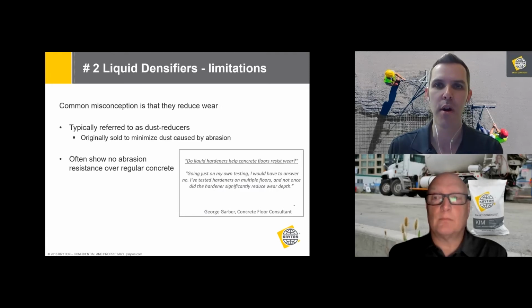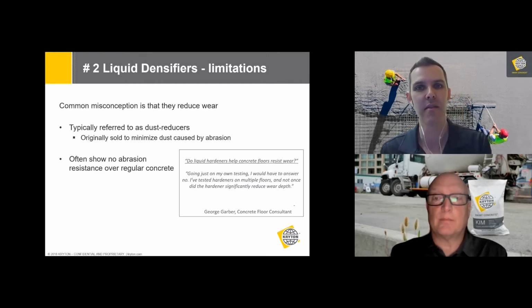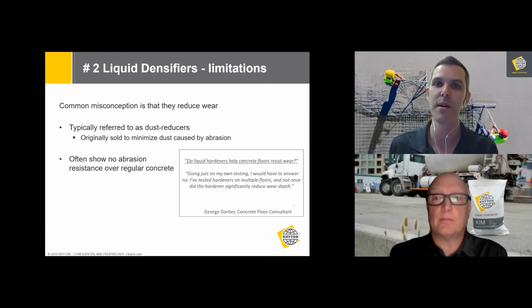Now, this basic reaction product of reacting with calcium hydroxide to strengthen the paste is quite similar to how SCMs work, such as fly ash, slag, or silica fume. So one of the consequences of using a liquid hardener is they may then start competing with your fly ash or slag for this calcium hydroxide. In fact, so much so that many suppliers of these products recommend limiting the amount of fly ash or slag you use in your concrete, or they may recommend delaying the application for up to 28 days because they want to allow the concrete to come up to its specified strength before you apply the hardener.